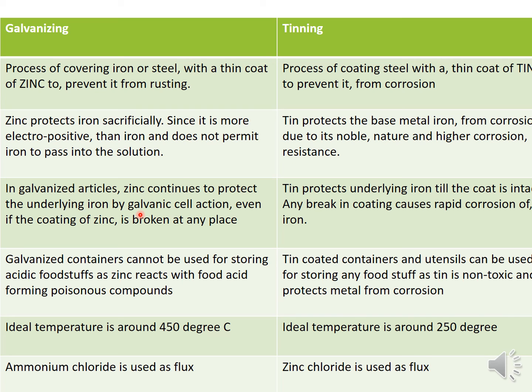In galvanized articles, zinc continues to protect even after the layer of coating is broken. Even if the coating breaks, zinc forms a galvanic cell and corrosion will not take place. If the tin layer breaks, corrosion will take place rapidly. Galvanized containers cannot be used for storing food as they form a poisonous compound by reacting with food acid. Tin containers are used for storing food and pharmaceuticals, as tin is non-toxic and protects from corrosion.